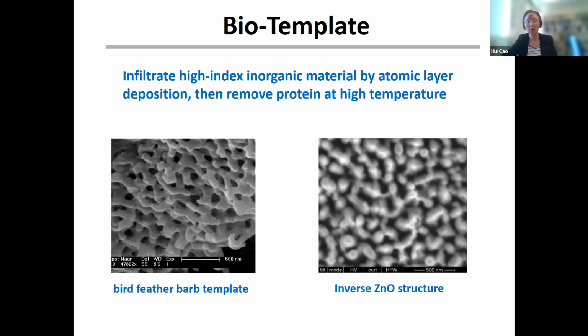So we take a different approach. We try to use a template, like from this bird feather. For example, this kind of soft matter has a template with very delicate structures, and then we try to infiltrate inorganic materials like titanium dioxide that has a large refractive index, or even zinc oxide that has an active response or nonlinear response. And then after we infiltrate the inorganic material into this bio template, we fire the sample at a high temperature to remove the protein, or we can also remove the polymer.